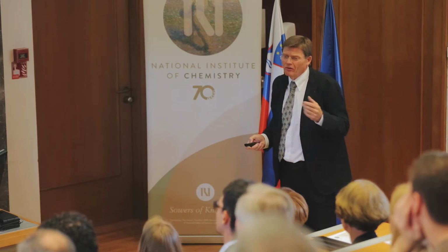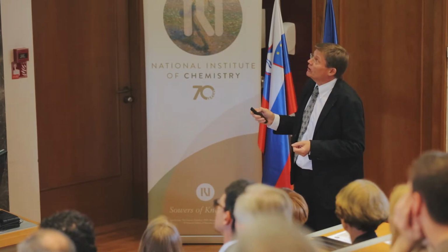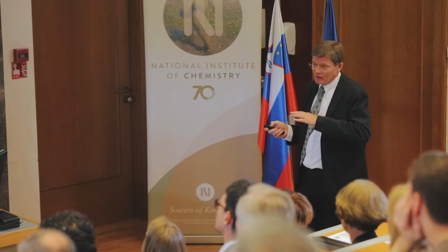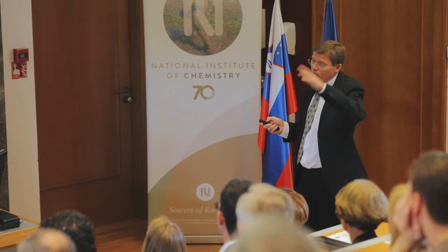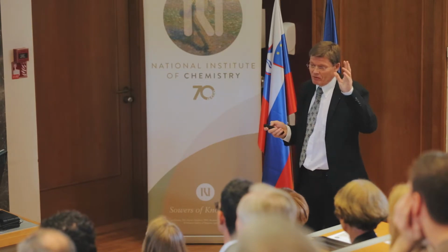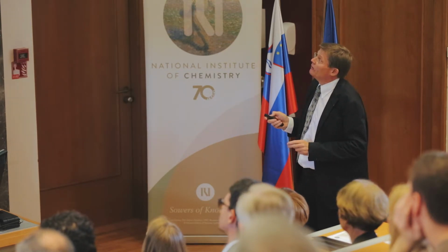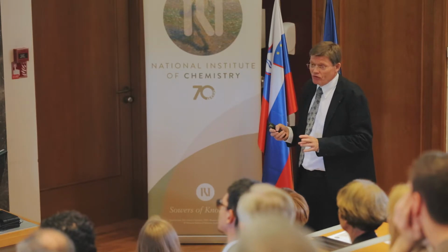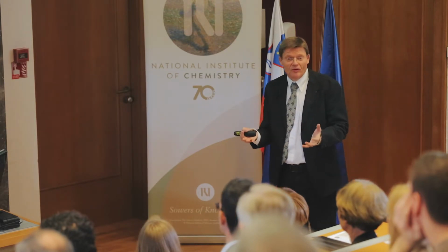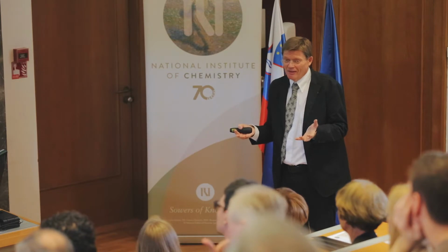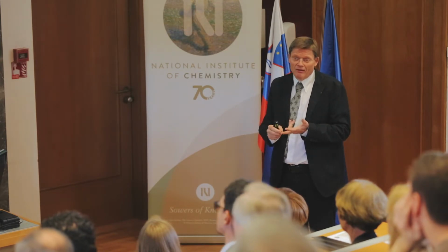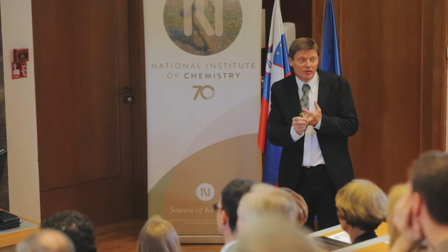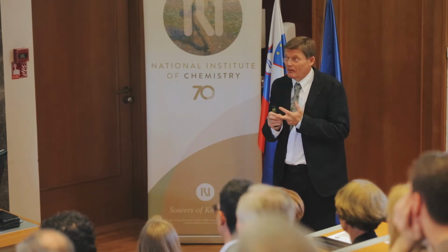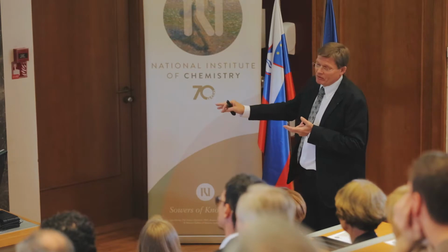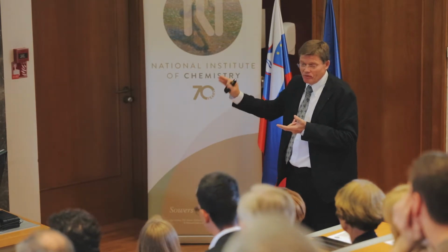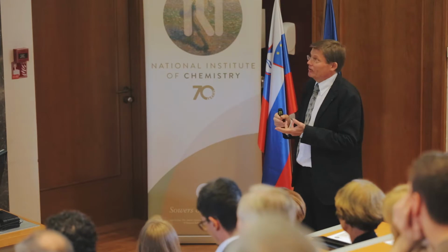But more recently, there's a lot of literature now on perovskites instead of these dyes, inorganic materials, and the efficiency went up quite a degree. But people not only reported better efficiency, they also said there are a lot of strange things going on. They call them anomalies. Such anomalies have been, for example, the dielectric constant appeared to be very high, but only at low frequencies. People thought this must be a sign of ferroelectricity, but naturally it's not ferroelectricity.